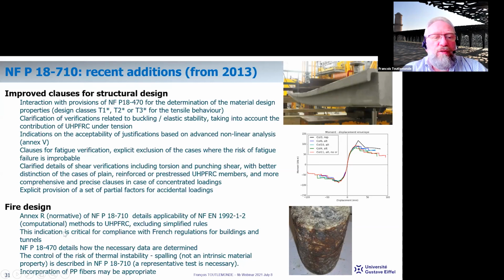Also the aspect of fire design, which is also a legal issue in France, was detailed with a normative annex which details the applicability of Eurocode 2 methods, excluding the simplified rules. Details are given to determine the material property and the control of the risk of thermal instability — spalling — and in general a representative test is necessary. In this case, the incorporation of polypropylene fibers is indicated as being generally appropriate.